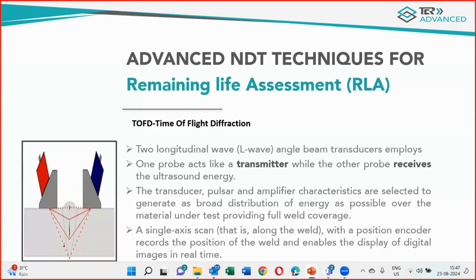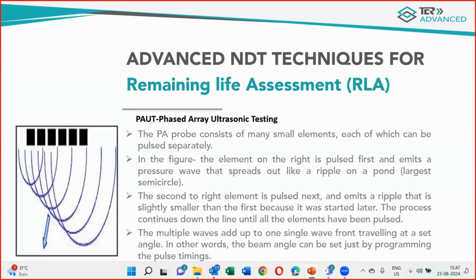Then, we have the other technique called phased array ultrasonic testing. Now, this is quite useful in identifying issues with the tube-to-tube weld joints. In PAUT, we have the bracelet probe, and these bracelet probes are put around the weld joint, and the entire joint can be configured. And TCR has done this at many companies. Unfortunately, testing is considered a labor job these days. So we lose a lot of jobs because of those aspects. But whenever there is a problem, people don't worry about the charges, and they call on us. We have all standard samples available with us for phased array ultrasonic testing.